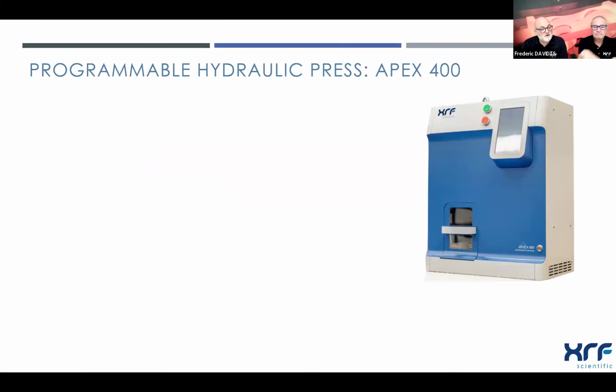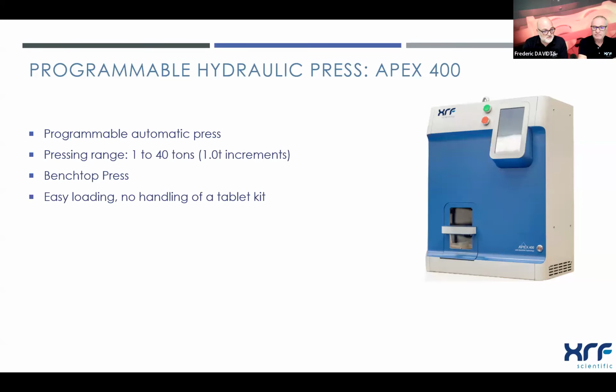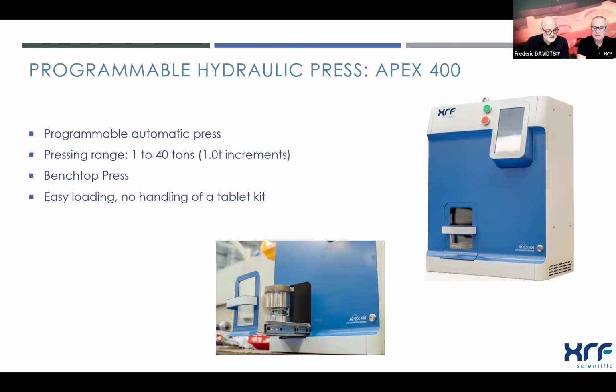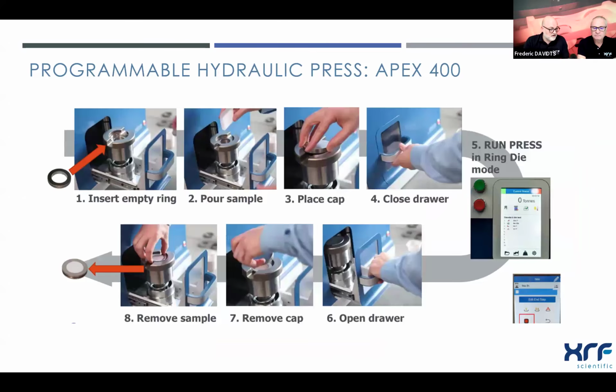And we have also a programmable hydraulic press, the Apex 400. So this machine is fully automatic. This machine is able to reach 40 tons, and it's a benchtop press machine. So 40 tons is quite rare. And the advantage is the easy loading with no handling of the pellet die kit. So it's automatically ejected. And we have a drawer to load in, load out the powder.